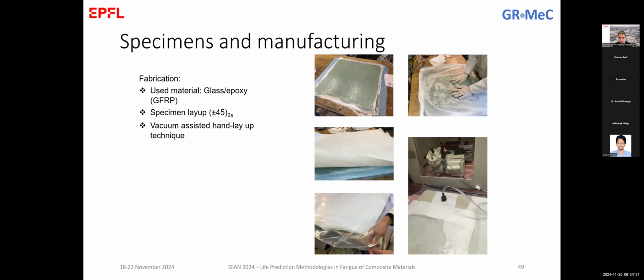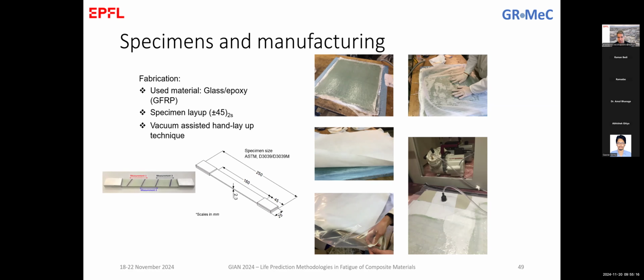So the material that was used was a glass epoxy laminate with plus minus 45 layup. We fabricated everything in our lab with a vacuum-assisted hand layup technique. I suppose you are familiar with this method, where we stack the plies in the orientation that we would like. We apply the resin by hand, and then we put everything in a vacuum to make the production more consistent. From these laminates that we manufactured, we cut specimens according to ASTM D3039, which defines these rectangular specimens with the tabs at the ends.